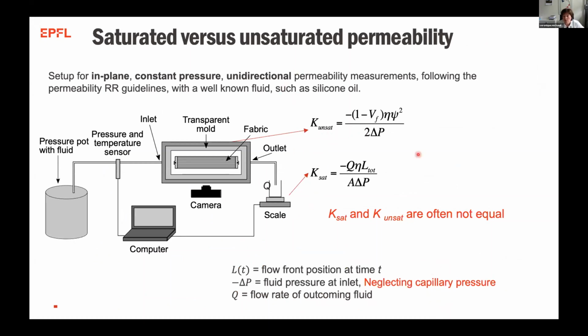And one thing we can do, when you measure this unsaturated permeability with the flow front, you can also, at the end, let the fluid flow through the outlet and measure the saturated permeability with the flow rate. So you know what is the flow rate that comes out, you measure it here, and you divide this by the full length of the fluid, the area of the textile, and delta P. And this time, because you don't have any capillary effects, because everything is fully saturated, delta P is the real delta P. So it's really the pressure here minus the pressure at the inlet. Whereas here, when you measure it, the delta P is wrong because you also say it's pressure here minus pressure at the inlet, but you forget about the capillary pressure drop.